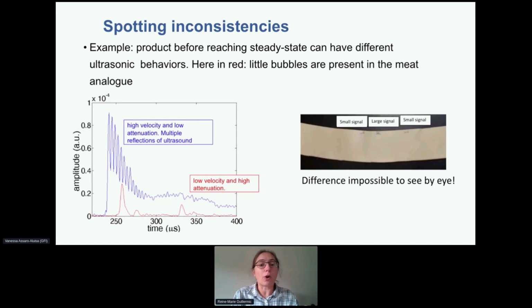Those two signals were obtained in a piece of extrudate where the steady state was not reached during production, and we were not able to see that by eye, but the ultrasound was able to pick up that there was a difference. In fact, what happened is that you had little bubbles present in the meat analog at that time. So, yeah, you can go forward.